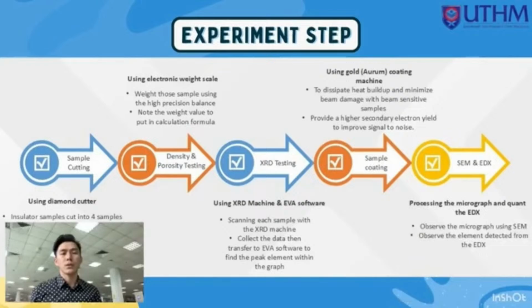Before we do the SEM and also the EDX testing, we need to do the sample coating first. Using the gold, which is the Aurum coating machine, the coating is to dissipate the heat buildup and minimize the beam damage with beam sensitive samples, and provide a higher secondary electron yield to improve signal to noise. Then you can do the SEM and EDX, processing the micrograph and running the EDX to observe the micrograph using SEM and observe the elements detected from the EDX.